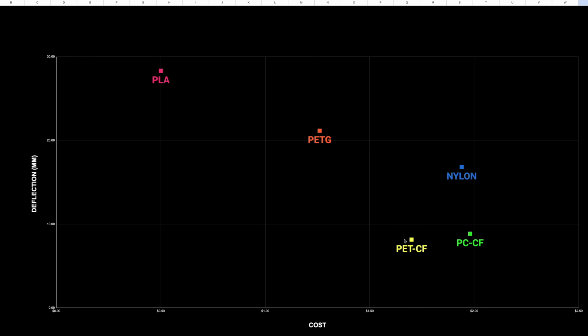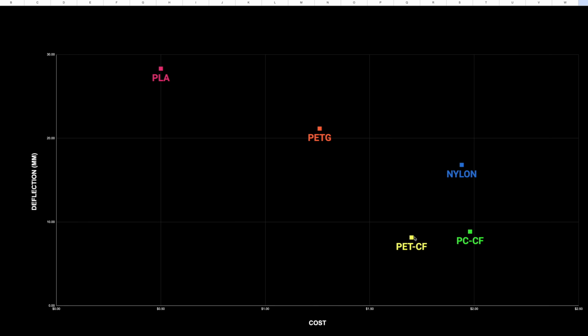The real standout here for me is the PET-CF because it hits right in the middle of that Venn diagram. Not only is it the best performer in terms of stiffness, the part cost is about $1.70. And for me, most importantly, it is as easy to print, in my experience, as the PETG, whereas the nylon and the PCCF were a bit fussy to print. So yeah, I'm really happy to find the sweet spot right here, the PET-CF. It's nice to have a standout that just makes sense in all the different characteristics.